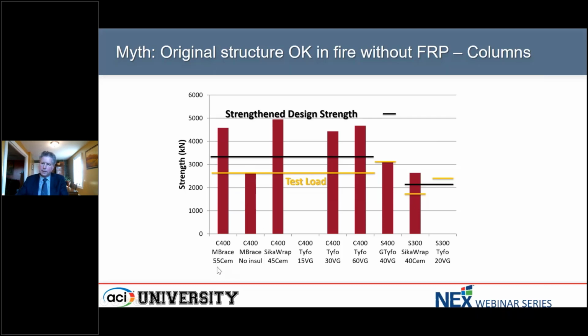One of the things here, you'll see at the bottom, talks about the insulation. So we had different thicknesses of insulation on these different columns. But you'll note that this one column here, we did test without any insulation. And so yes, no problem, it could carry the loads without the FRP for the test load. But what happened is this column failed after about 3 hours of fire exposure, which might be okay in certain circumstances, but certainly didn't get the fire resistance of over 4 hours that all the other columns had. So that's where applying some insulation can be beneficial, even if you're in that category that I mentioned, where the original structure can carry the loads in the fire.